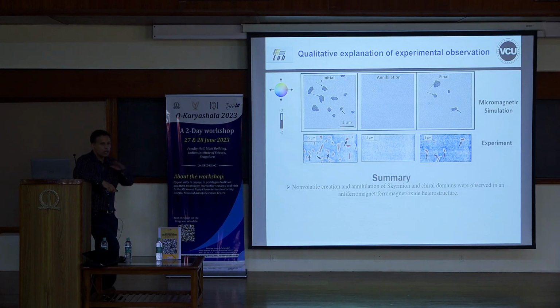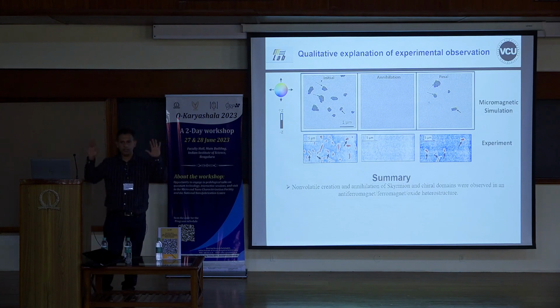In other words, no magnetic field applied, pure electric field, we are able to destroy and create for many cycles, and this is like initial, annihilated state, final state. So what is happening here, if you want to know more, if you go back to the slides, when I don't put any field, I have this large anisotropy, right? But then if the anisotropy is lowered, there is this thing that says don't be parallel, go perpendicular, right? So you form this skyrmion state.